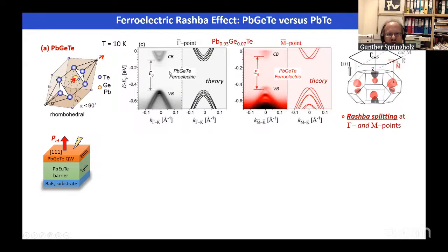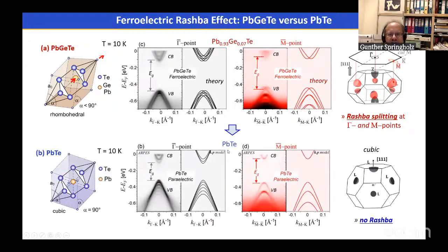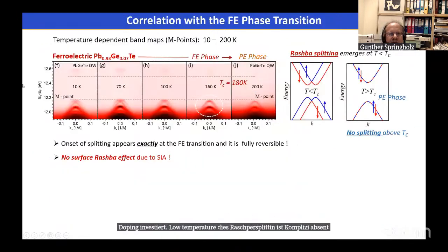So at low temperature, we again find this Rashba splitting, both at the gamma point and the M point, where we observe that at the M point, the Rashba splitting is obviously larger. And we can compare this to the measurements for lead telluride without germanium doping, and we see at low temperature, this Rashba splitting is completely absent. We can also look at this as a function of temperature. This is shown here for the M point.